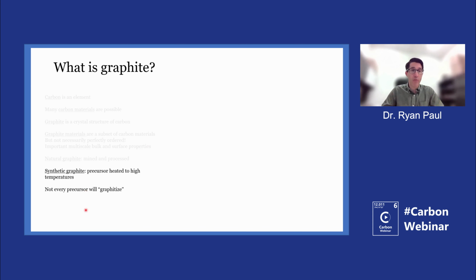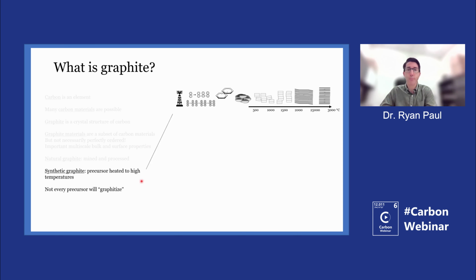The other version of graphite, and probably the dominant one today, is synthetic graphite, where there is a carbonaceous precursor that is heated to high temperature. An example of this could be a petroleum or a coal-based aromatic compound. Could have some other heteroatoms in it as well, but these aromatic compounds can be heated to high temperature, and if you get the right type of aromatic compounds, that will allow for this liquid crystalline or this mesophase formation before starting to completely polymerize.